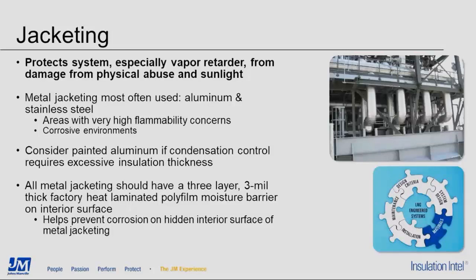And in all cases, the metal jacketing should have a 3-layer, 3 mil thick, factory laminated polyfilm moisture barrier on the interior surface. This helps prevent the corrosion on the interior surface of the metal jacketing, which will manifest itself in pitting, and pitting becomes a hole. And you don't want holes in any of the jacket systems in LNG applications.